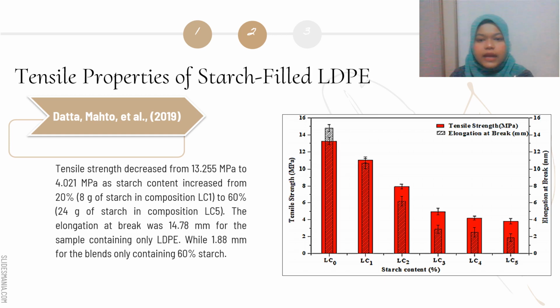The elongation at break was 14.78 mm for the sample containing only LDPE, while 1.88 mm for the blends containing 60% starch. The high porosity generated in the structure reduced the ability of the blended films to lengthen when stretched at a constant load, resulting in rupture after a slight elongation.